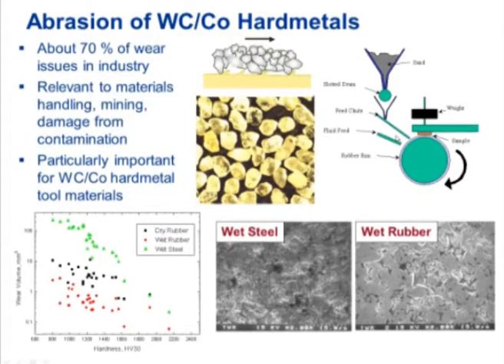So we modified the ASTM G65 test. We have a rubber lined wheel, and a chute that we feed the abrasive down. In this case, we have a fluid feed, and we press the sample against the rubber lined wheel, and the abrasive goes down the chute and through the interface and causes damage to the sample, which we evaluate by measuring weight loss and looking at the wear surface. This shows changing two things, dry or wet, and the actual material of the wheel. In two cases we have a rubber rim, and in one case we just have a steel wheel.